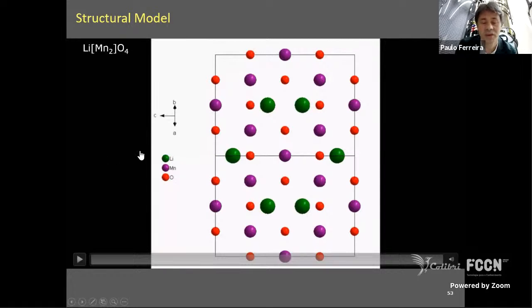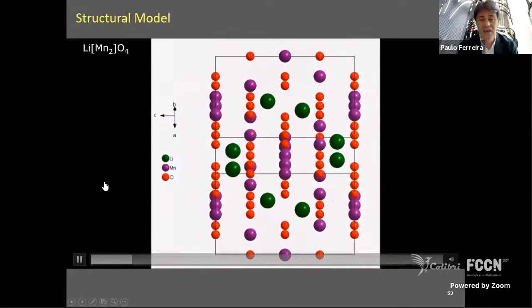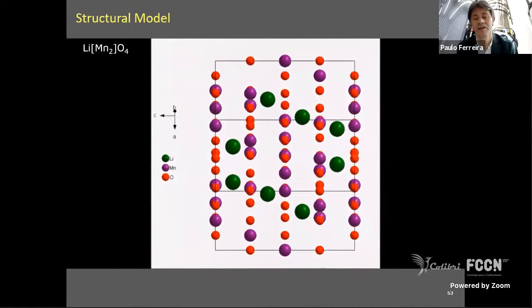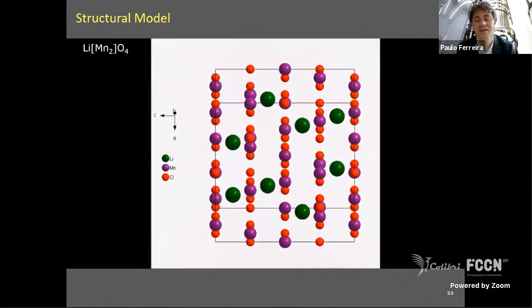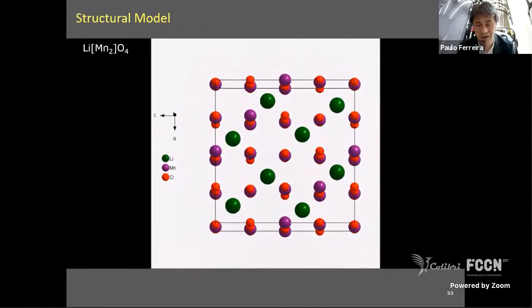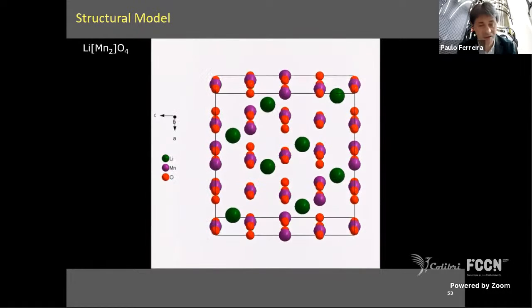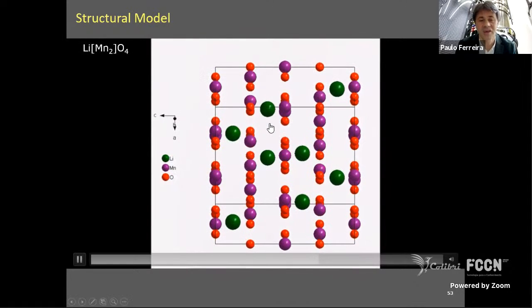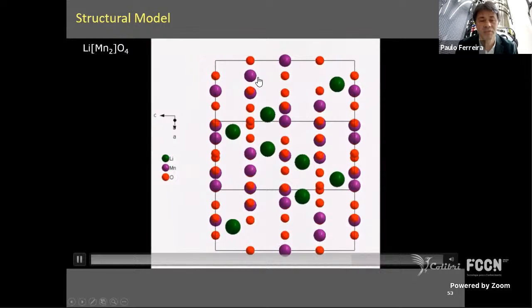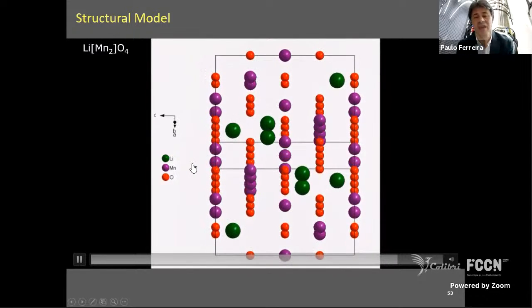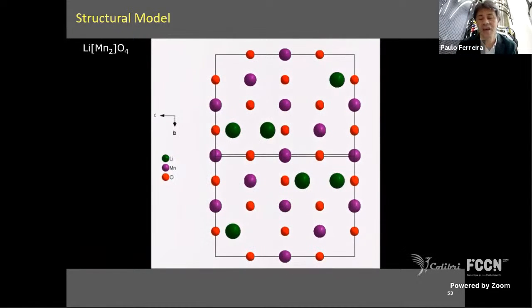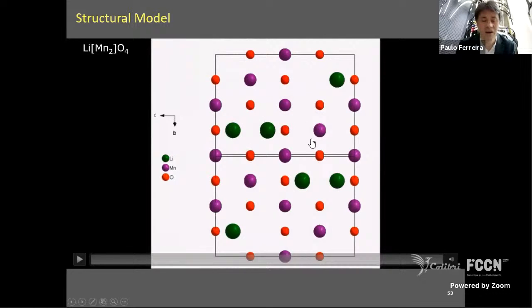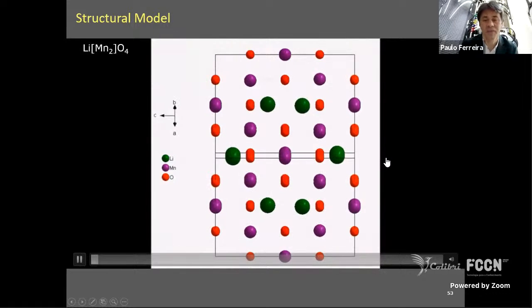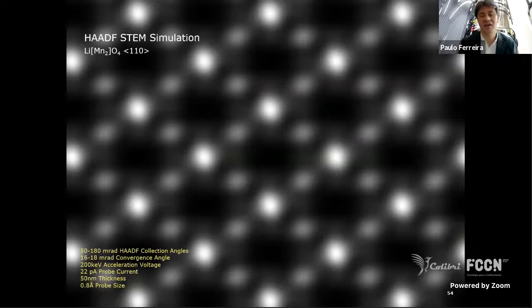So what we do, for example, is look at the atomic structure. First we look into the atomic model. We build these models to really understand the position and the orientation of these structures. So for example, here, the lithium in green, the manganese in purple, and the oxygen in red. And we would like to orient this in a way as, for example, this one, where the atoms are on top of each other. When we do that, this is a computer simulation of the structure.